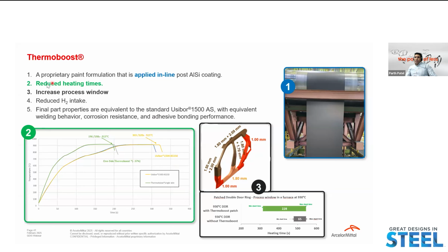We have this proprietary paint formulation applied on the line after the AlSi coating is done, and it's a degradable paint that reduces heating time. The paint absorbs more heat and heats faster, which increases your processing window. Once you reduce heating time, it also reduces your hydrogen intake because it spends less time in the oven.